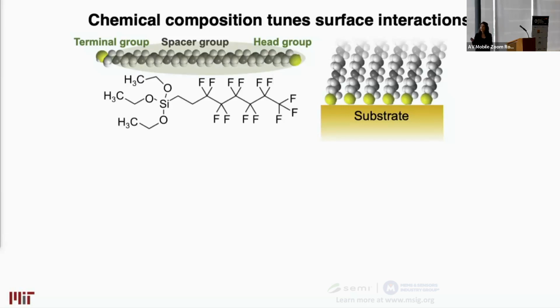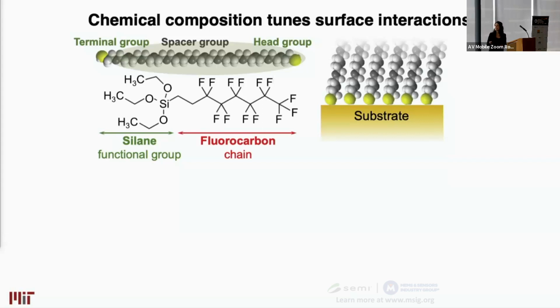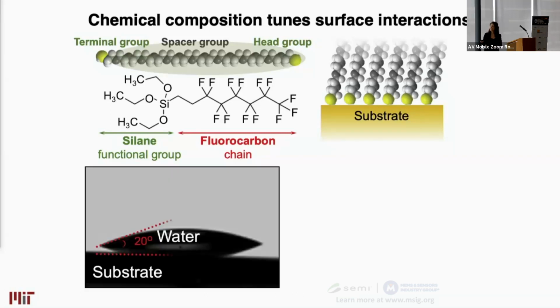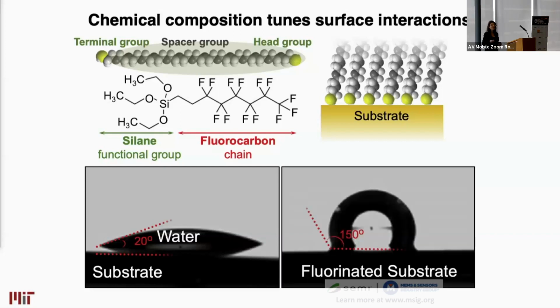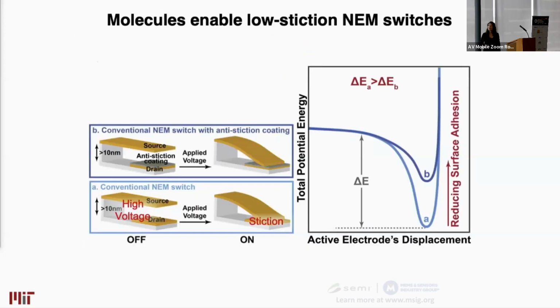To give you an idea, here I have a fluorosilane molecule. The silane end group allows functionalization onto surfaces like silicon oxide. The fluorocarbon end allows us to make the surface assume a lower surface energy property. So here is the water contact angle on a surface of silicon. And if the surface is functionalized with a monolayer less than 1 nanometer thin of this molecule, we get a drastic change in contact angle, suggesting how you can engineer the surface interactions through use of just a monolayer of molecules.